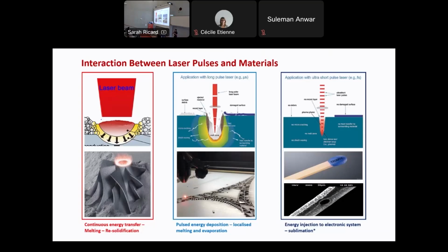In the ultra short regime, the laser photons interact only with the electrons of the surface, and then they're no longer lasers. What happens afterwards is that the electrons transfer the photon energy into the atoms, and then atoms may leave the surface, a big explosion, and so on and so forth. By this, there's no heat transfer involved. As a consequence, you can have very precise laser micro and nano processing. Here, two showcases: engraving on a matchstick and drilling a hole in a human hair.